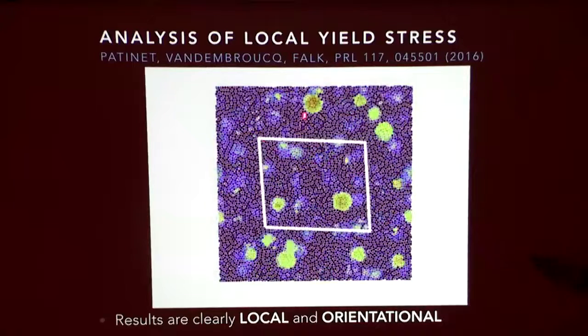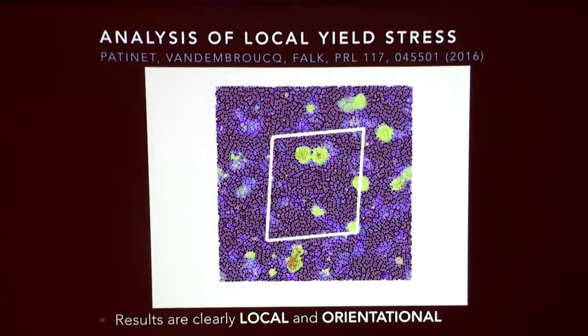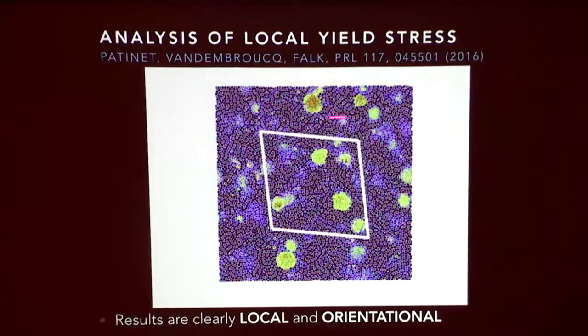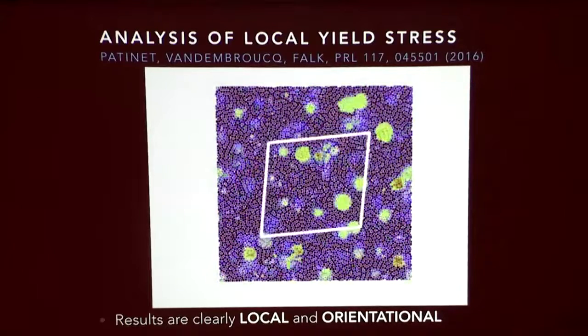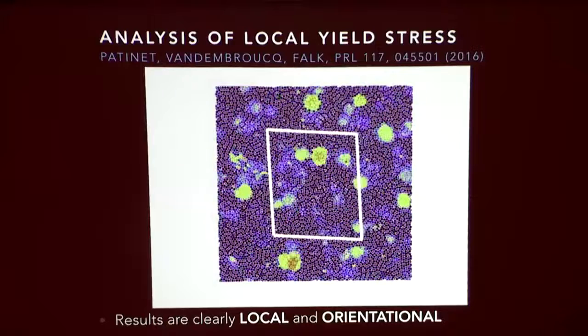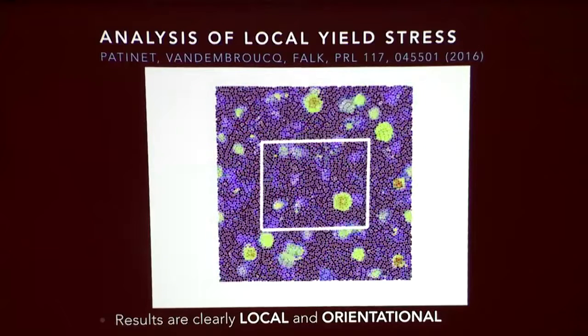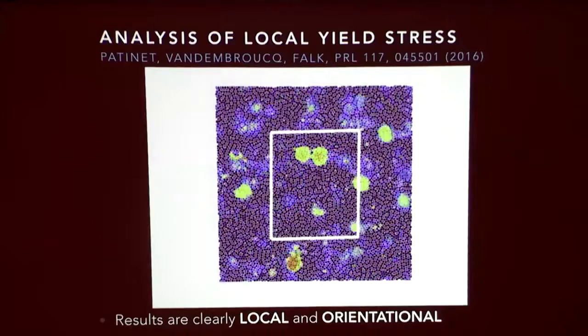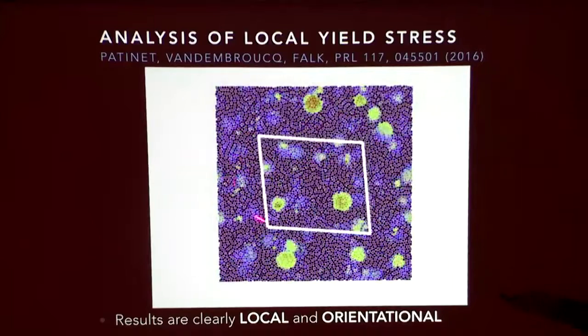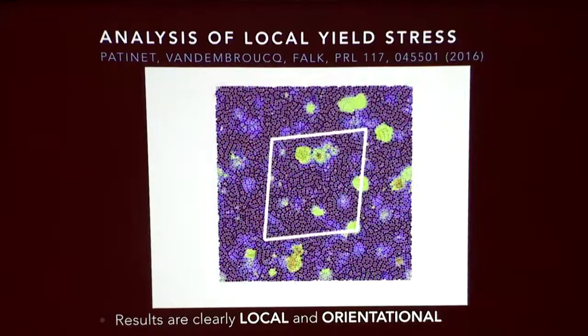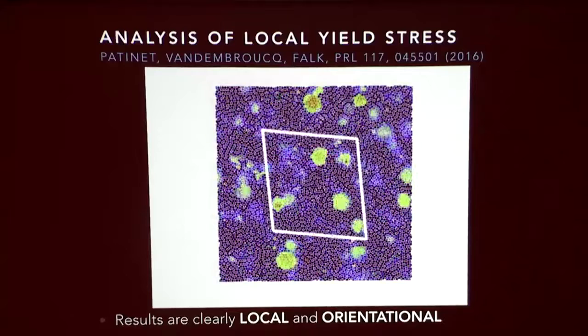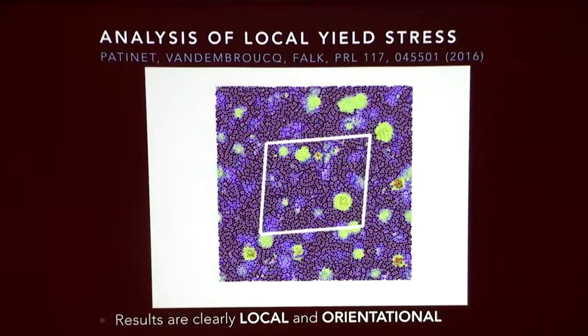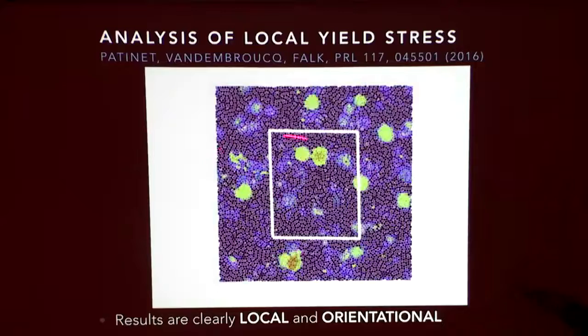But here what we're doing is cycling through the local yield stresses, yellow being low local yield stress, along the different orientations of local solicitation. The square in the middle shows the kind of deformation being applied locally around each probe as it changes shape.